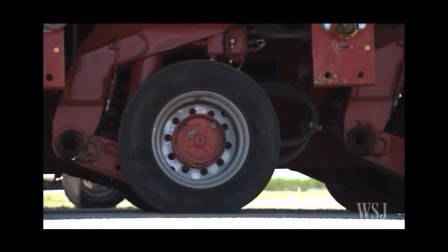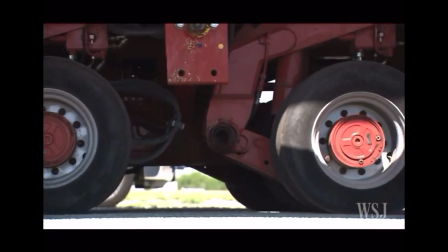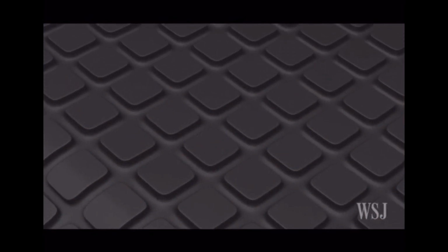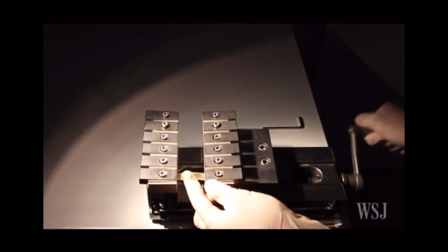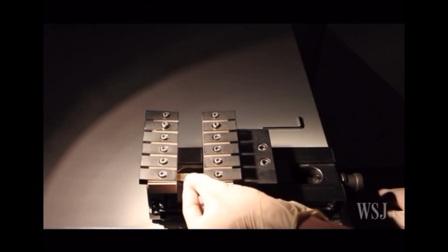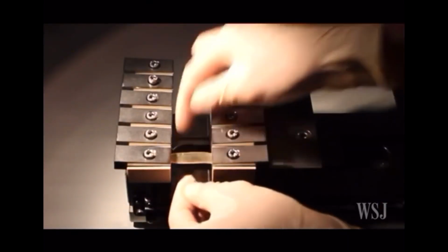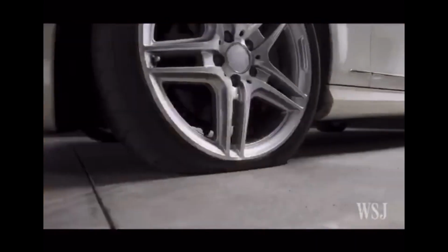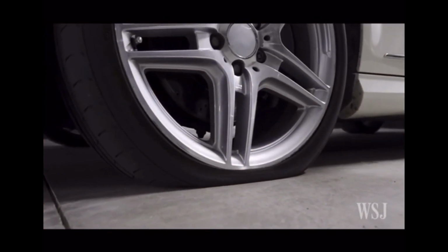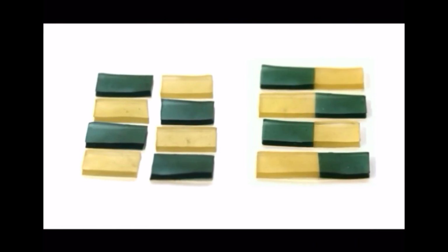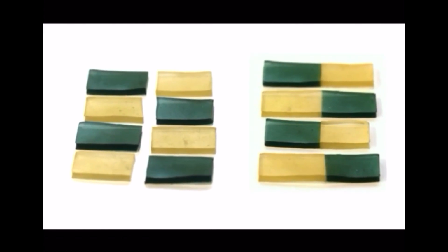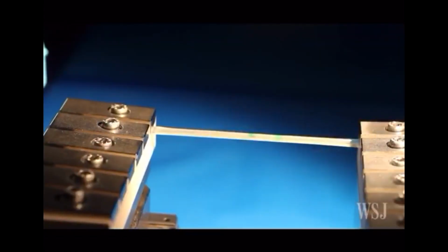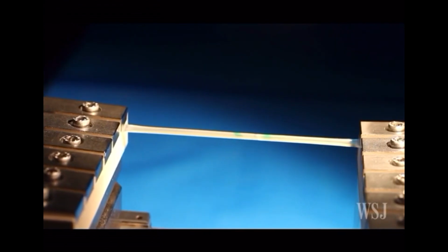Scientists have attempted to develop self-healing rubber in the past, but many of the prototypes produced couldn't achieve long-term stability. This study's researchers say their tests have shown that the new type of rubber can heal itself at room temperature, so a car tire could fix itself while just sitting parked in a garage. Heating the material to 212 degrees Fahrenheit shortly after the cut made the rubber heal even faster, and after 8 days, the rubber was capable of withstanding stress equivalent to 20 times the normal amount of pressure on a tire.